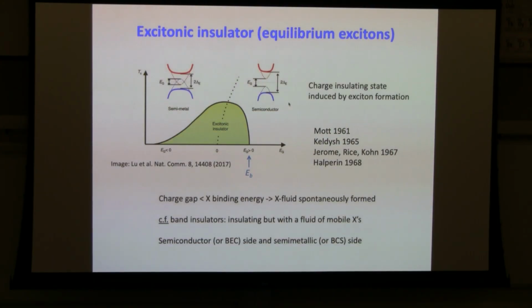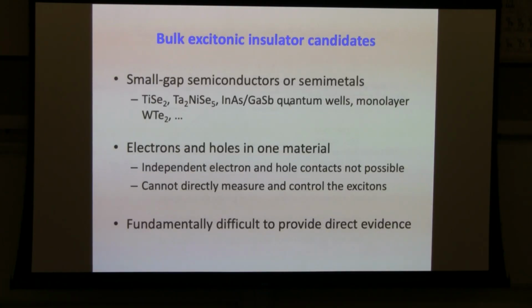It's called an excitonic insulator. Compared to a band insulator, it's also a charge insulating state, but it actually supports a fluid of mobile excitons in the system, which is charge neutral. It's harder to detect. And it's also divided into the semiconducting side, where the band gap is larger than zero, and the semi-metallic side, where the band gap is smaller than zero. And on both sides, you can support an excitonic insulator with a fluid of excitons in the system. And that's also known as the BEC limit or the BCS limit.